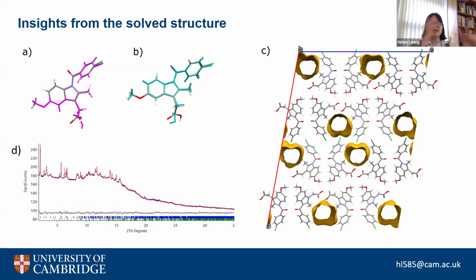And you can imagine, with large channels in your crystal structure and a relatively volatile solvent, that it is evaporating quite easily. And so what we were able to do is remake and reproduce this polymorph just using the solvent now, and taking away any PVP, so any of this amorphous polymer. And we were able to prove to ourselves that this was the mechanism for crystallization. So I guess this is just one example of where the direct insights from the structure have led to a real life benefit in the manufacturing techniques.